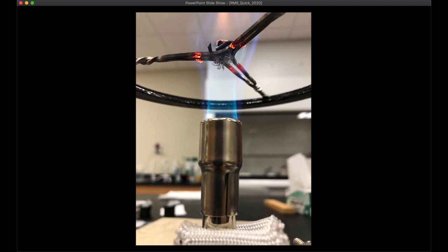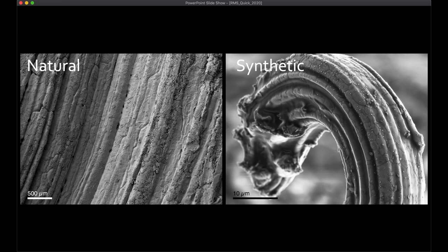Comparing the textures of natural and synthetic specimens revealed that wire silvers in general are polycrystalline aggregates, and that the striations are merely superficial features. These are scanning electron micrographs of representative natural and synthetic wire silvers. If you look closely, you can see the grain boundaries expressed at the surface. We've also analyzed the bulk crystallinity with energy-resolved neutron resonance imaging, which confirms the textures we observed at the surface. In some specimens, there can be a small degree of preferred crystallite orientation, but overall, crystallites can be found in virtually any orientation within a given specimen.